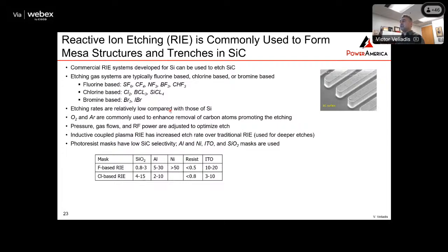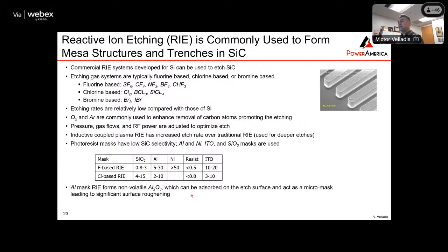And these are some of the mask materials. You can see that if you use resist, that's commonly used in silicon, the selectivity is very, very low. So you eat away the resist layer at twice the rate that you etch the silicon carbide. So therefore, oxide is a good solution with a chlorine-based RIE. It can give you a selectivity anywhere between 4 to 15. And then you can use aluminum and nickel as metals, although metals are not preferable in a manufacturing environment.